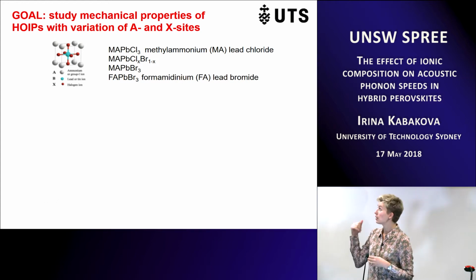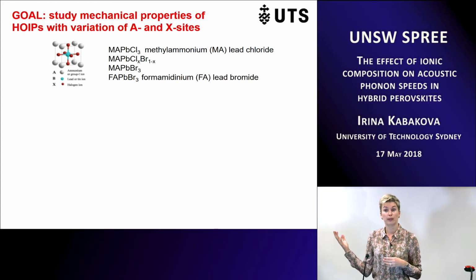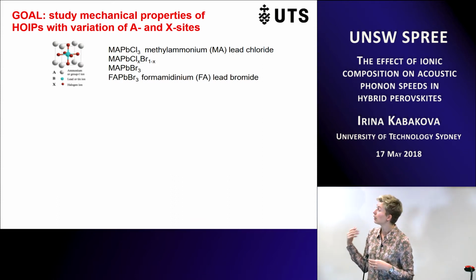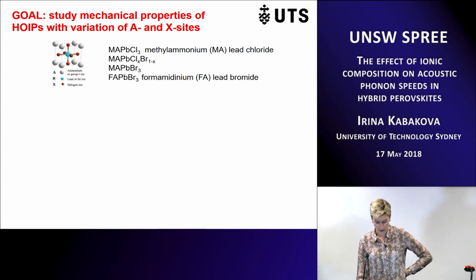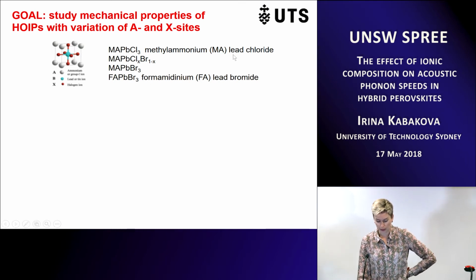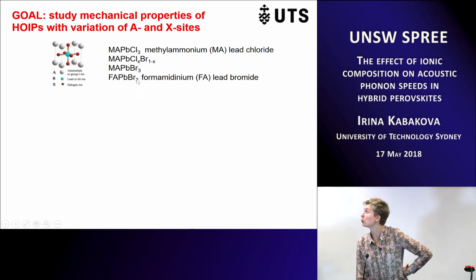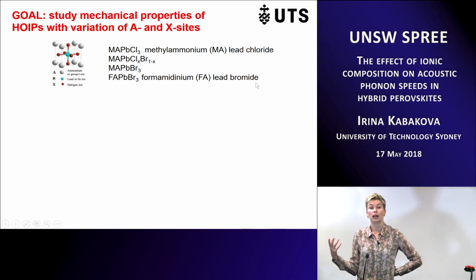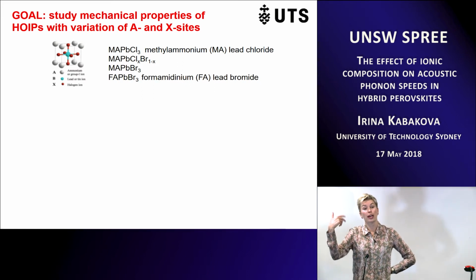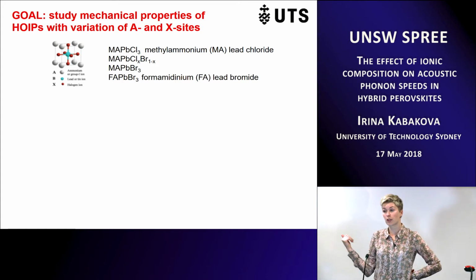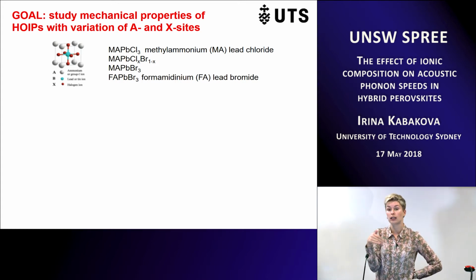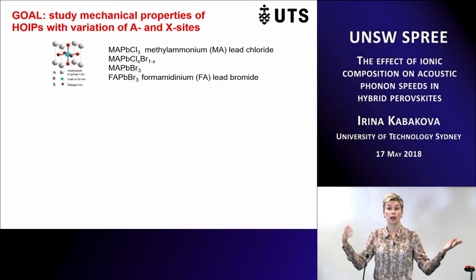So we decided to take a bunch of different perovskite crystals with slight variety in their composition. Here you have methylammonium lead chloride, bromide, and the mixture chloride-bromide. We could also substitute the cation, the organic molecule, with formamidinium, and obtain formamidinium lead bromide. Thus we can change the X site, which is the halogen atom, or the A site, which is the organic molecule, and see how it affects